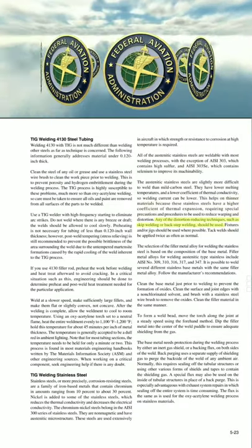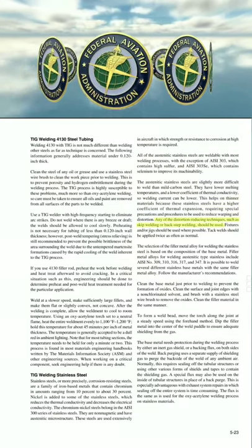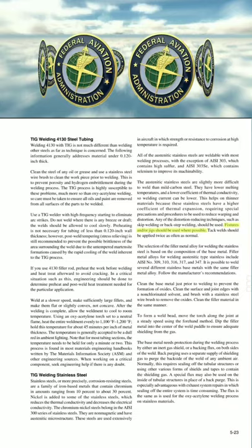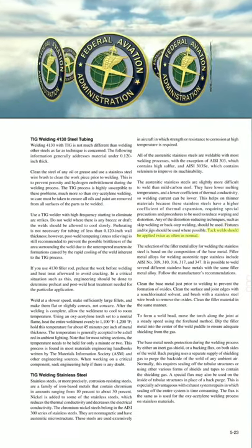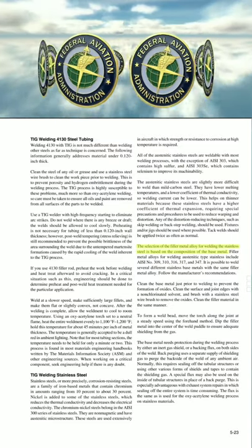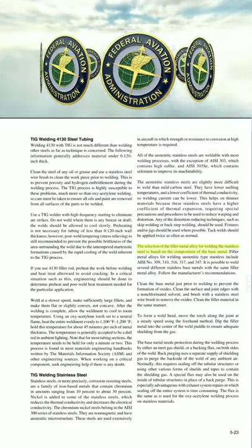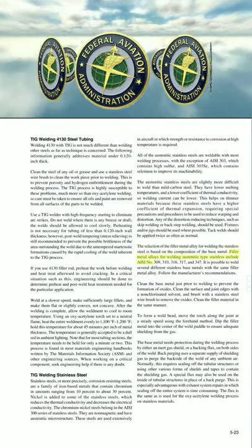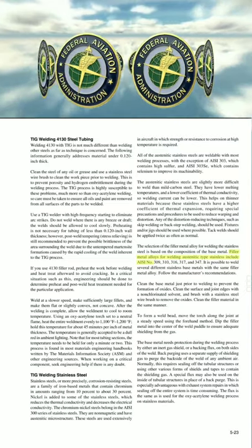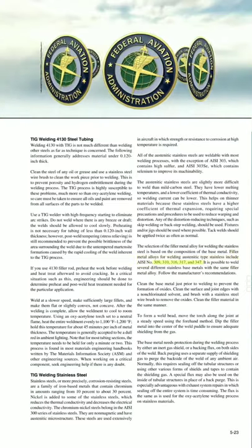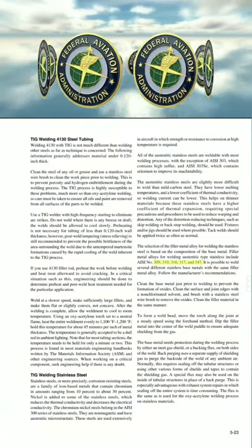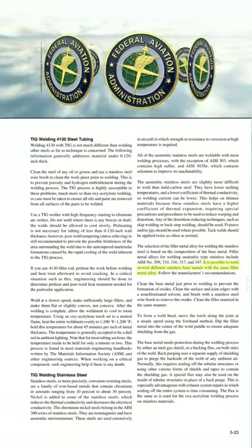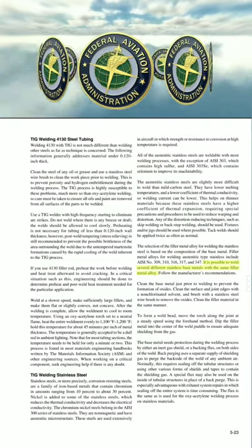Any of the distortion-reducing techniques, such as skip welding or backstep welding, should be used. Fixtures and/or jigs should be used where possible. Tack welds should be applied twice as often as normal. The selection of the filler metal alloy for welding the stainless steel is based on the composition of the base metal. Filler metal alloys for welding austenitic type stainless include 309, 310, 316, 317, and 347. It is possible to weld several different stainless base metals with the same filler metal alloy.